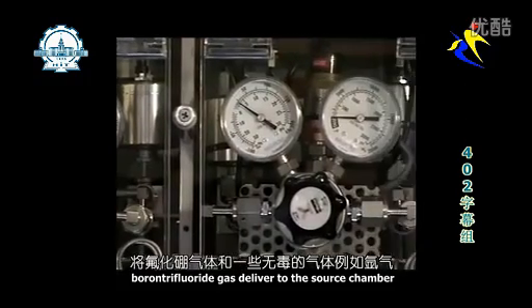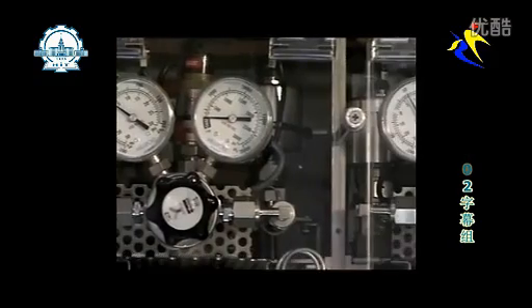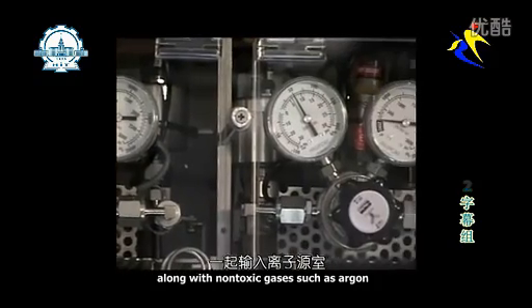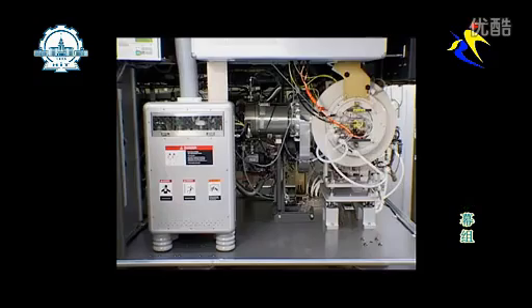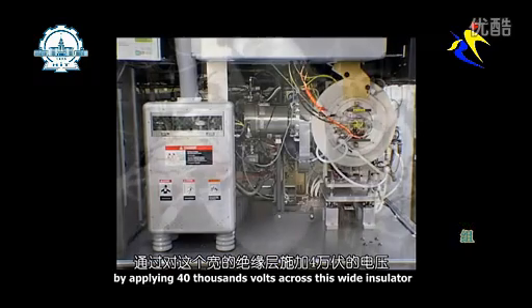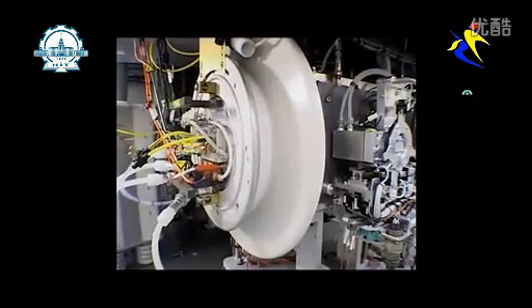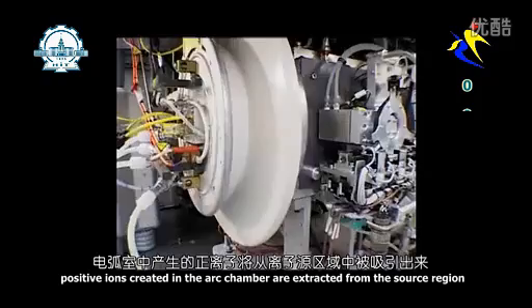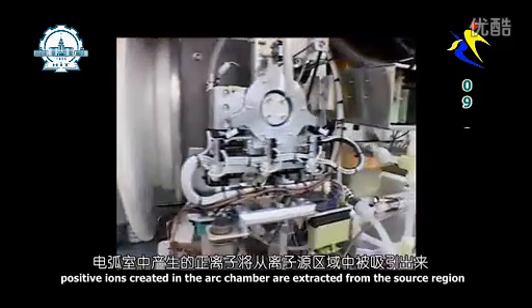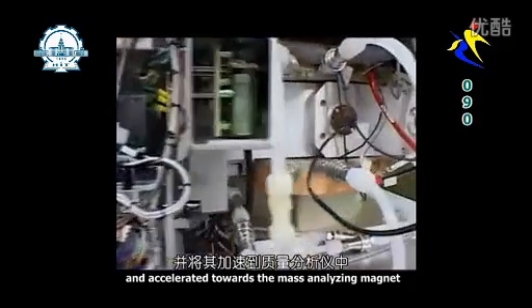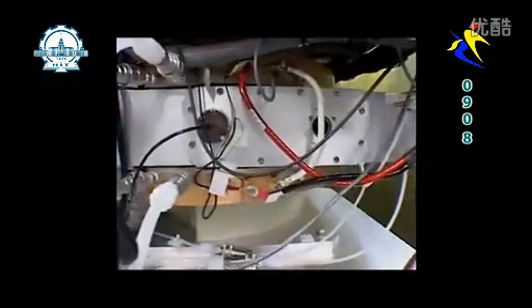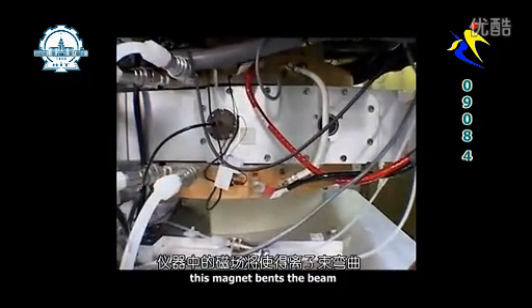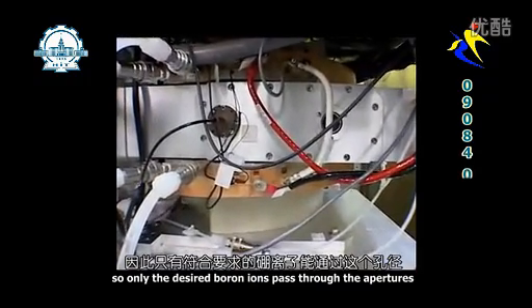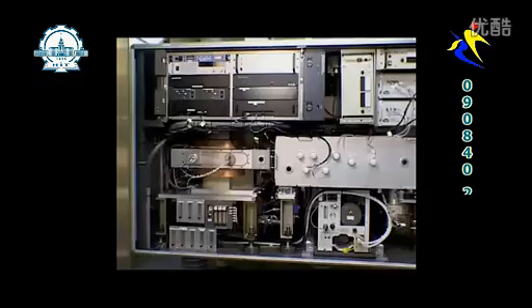Boron trifluoride gas is delivered to the source chamber, along with non-toxic gases such as argon. By applying 40,000 volts across this white insulator, positive ions created in the arc chamber are extracted from the source region and accelerated towards the mass-analyzing magnet. This magnet bends the beam, so only the desired boron ions pass through the apertures.